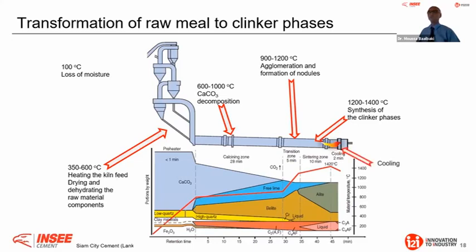And after that, we come to the cooling. Therefore, we have to quench the clinker very fast to keep its reactivity. This transformation will take about, let's say, 1 hour, and we can produce, for example, one of the largest kilns in the world, owned by our group in Saraburi, up to 10,000 ton per day. In Putna we can go up to 800 to 900,000 ton of clinker per year. This is our production capacity. That is important that we know when we come to standards, when we talk about clinker. This is how clinker is produced.